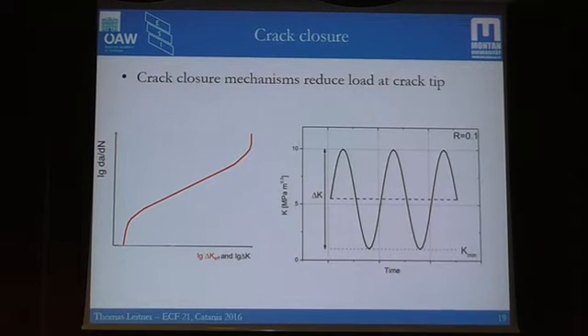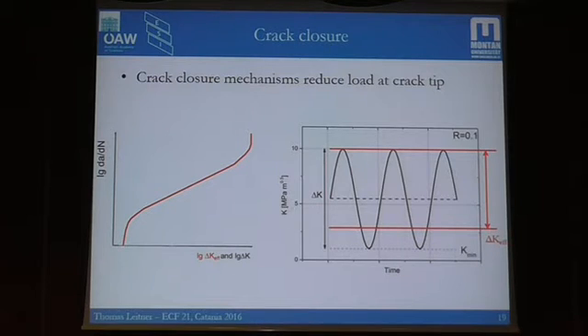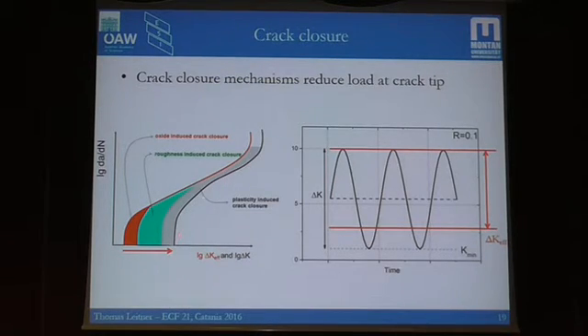So what's the reason for this? Well, basically, crack closure mechanisms reduce the load at the crack tip, so it gets to premature contact of the crack faces during unloading. So we don't have the full delta K range acting at the crack tip anymore, but the reduced, effective delta K. Thereby, we need a higher global delta K for the crack tip to experience the same delta K. So basically, the curve we measure here is shifted to higher delta K values due to severe contributions of crack closure. For the higher mean stresses, we also have higher delta CTOD, higher crack tip opening displacements, and therefore the contribution of crack closure is much reduced. So we measure more like this curve here, without the crack closure contribution.